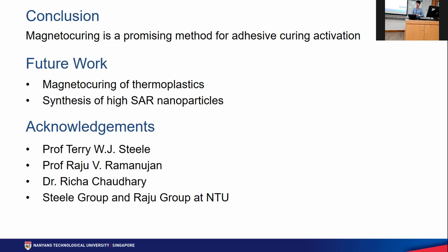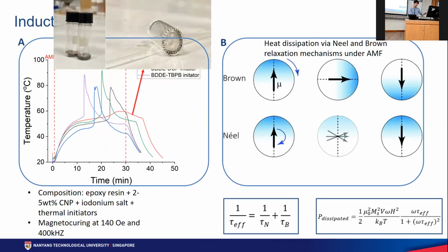What about magnetic alignment? Will it affect it, if you align those particles? Well, the closest I got to that is this: when I start with the liquid resin, it is a black liquid, but when I put it inside an AMF coil, these actually align to the magnetic field, and I guess they become like localized spots dissipating heat from the sides into the middle part. That's what I observed, and that's the only alignment that I observed.